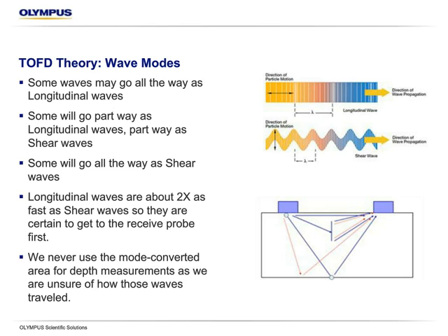So when we're dealing with TOFD, we have to be aware that we have both of these wave modes present. We can see the diagram on the bottom, again showing a lot of things can happen. We send out a longitudinal wave with time of flight diffraction. It starts as a longitudinal wave, but when it hits a flaw, we also have mode conversion there. So almost every incident where we use sound, every time that sound strikes something, usually different wave modes are generated.